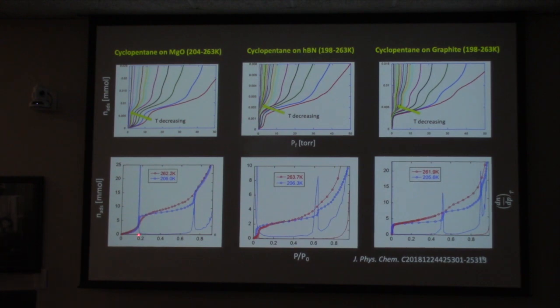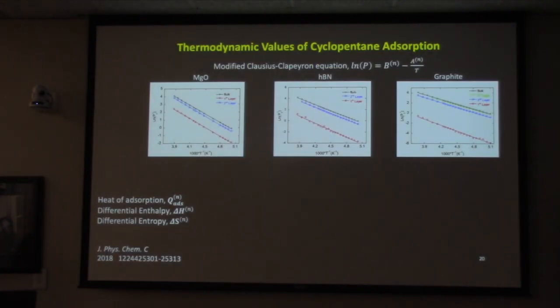And in fact, what you can do is you can take the derivatives of these individual layer transitions and see how they change as a function of temperature and as a function of composition of either the molecule or the surface. And you can learn things like heats of adsorption, the differential entropy, and if you care about this, you can read it in a number of publications. You can do what's called modified Clausius-Clapeyron. That just allows you to follow how it is that these thermodynamic quantities exist. Go to the Bureau of Standards and you can find this out from years ago for all of the variety of molecules, etc.